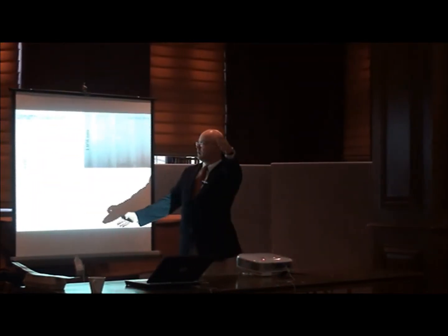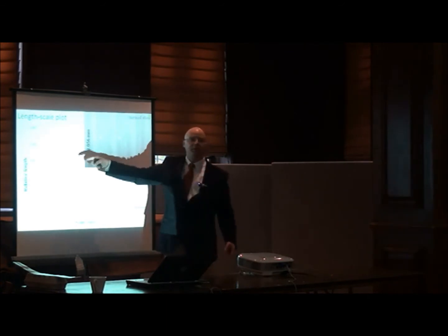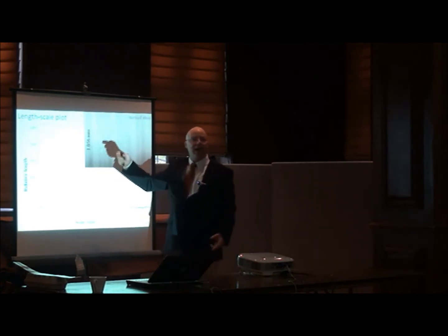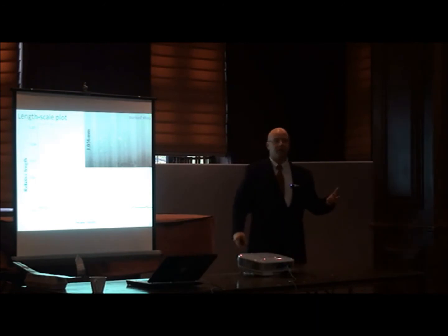But we typically get a long region, so this is 1, 2, 3 decades long of a linear fit here as we get down to finer and finer scales on the surface. So if we look at the complexity from profiles taken in this direction and compare it to the complexity of profiles taken in this direction, these profiles are more complex. And so now we have two numbers. We could say there's this ratio of complexity in one direction to the complexity in the other direction. So now we can quantify how much direction there is on the surface.